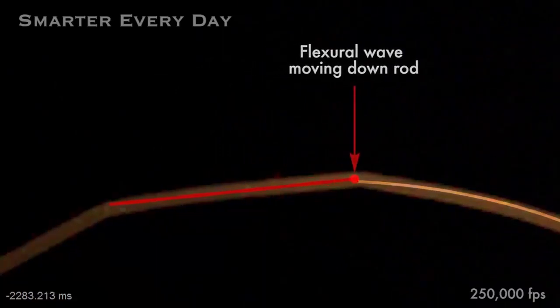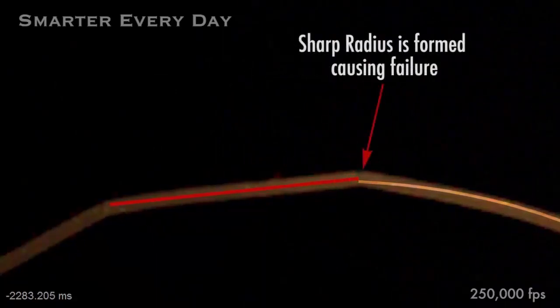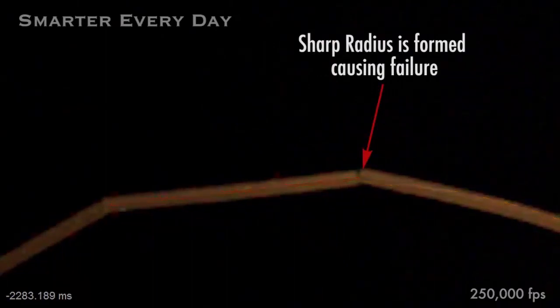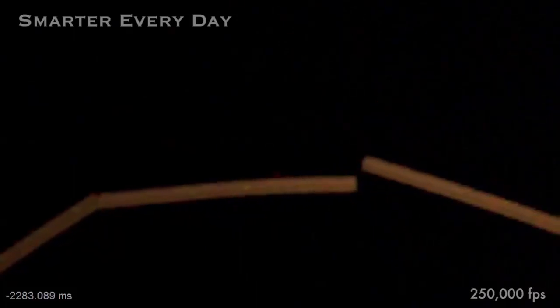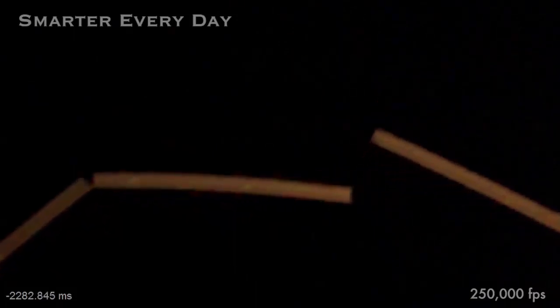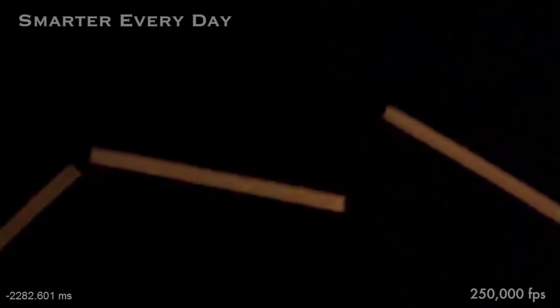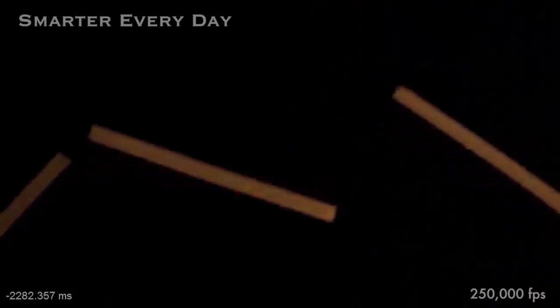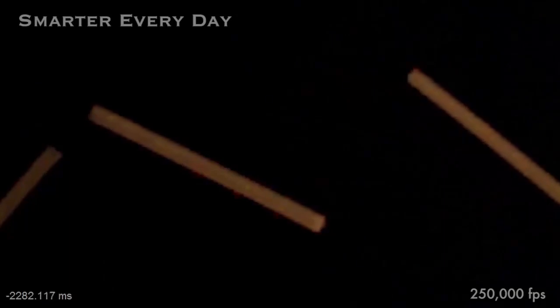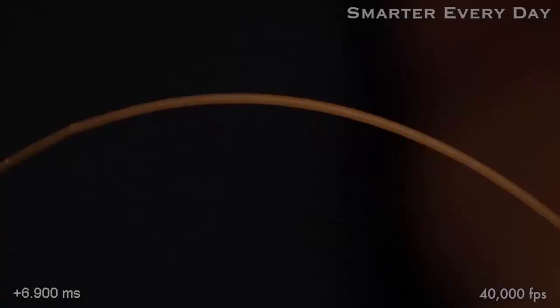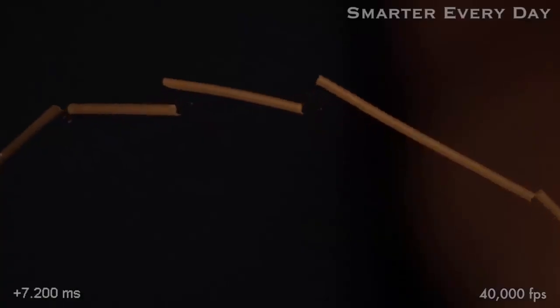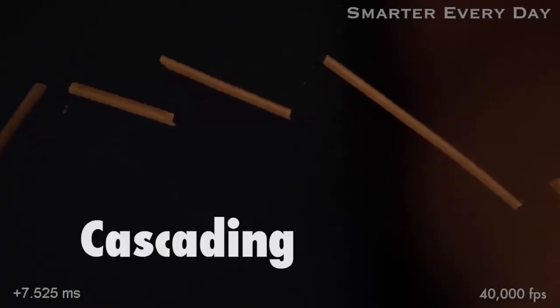Because the spaghetti on the left is already straightened out and the spaghetti on the right is still curved, the point where they meet is now even more curved, which causes the spaghetti to bend beyond the minimum failure radius. This results in a fracture. It's like one side doesn't get the message fast enough. If the whole rod were to release at one time, it'd be fine, but it doesn't. It breaks itself apart along the way. Every time you have a new break, the process starts all over again. This physical phenomenon is called a cascading fracture.